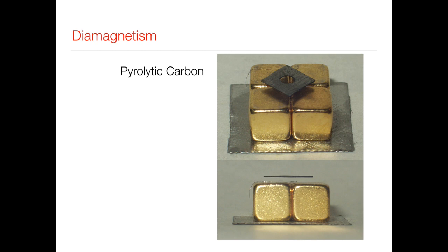Okay. Now, for most diamagnetic materials, the diamagnetic effect is sufficiently weak that it's hard to notice the effect of the external field. The material that has the largest diamagnetic effect per weight is actually something called pyrolytic carbon. So this is carbon that's mainly comprised of sp2 carbons, so it's quite graphite-like, but it's not as perfect as graphite. There's lots of connections between the different layers. Okay, this has a reasonably large diamagnetic susceptibility, but we're still actually talking about the order of 6 times 10 to the minus 5, that type of effect. So it is really small,